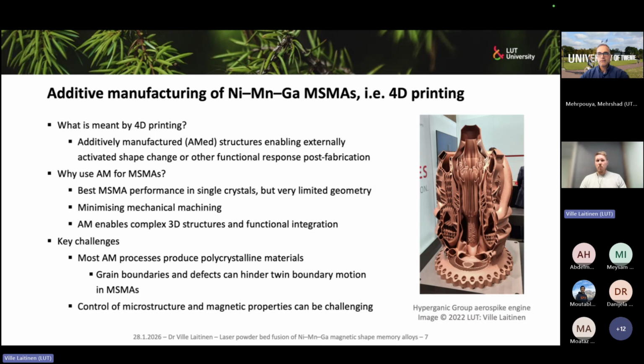And why we want to use it for nickel, manganese, gallium is that first, although we observe the best functional performance typically in single crystals, we are very limited with geometry. Most of our single crystals are these very stick-like features cut from a single crystal, and you can only do a limited number of devices with that kind of geometry.